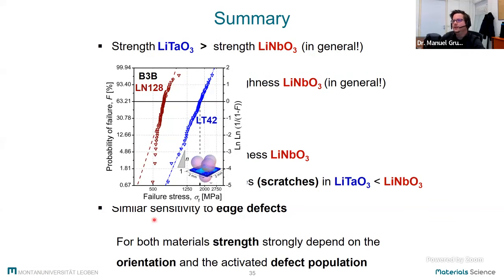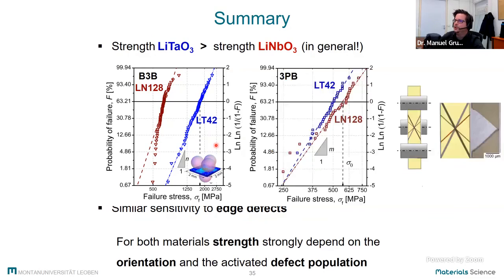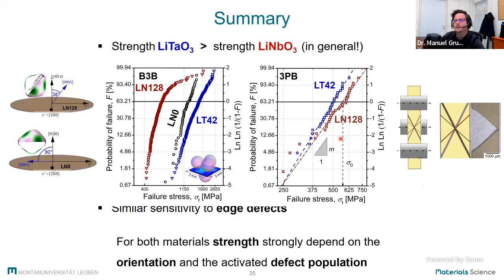So as we can see here, we can measure much higher hardness strength for lithium tantalate compared to lithium niobate for this biaxial configuration. But if you only do, for example, three-point bending, it can happen that if you take an unfortunate orientation, you can even measure higher strength values for lithium niobate compared to lithium tantalate. And also the orientation of the wafers can play a huge role. So by only changing the orientation of the wafer, a doubled characteristic strength can be achieved for this kind of materials. So now I'm at the end of my talk, and I hope that there are some questions.